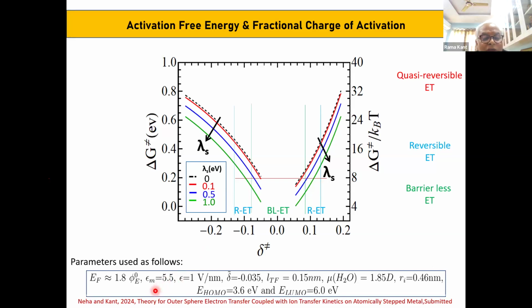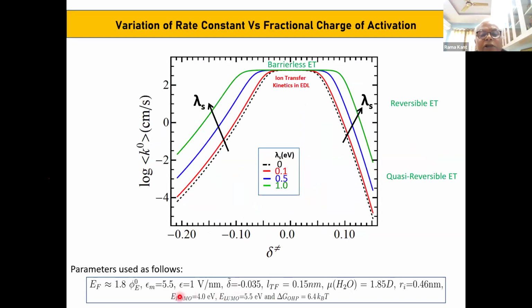To plot this, because we have made a continuum plot, we have assumed that the Fermi energy is approximately equal to 1.8 of the work function. This we averaged over various Fermi energies. It's not true for graphene. For good metals, this formula is a good approximation to plot. Then reorganization energy, Thomas Fermi length, size of the ion, dipole of water, HOMO and LUMO energy: these are the input parameters you require to run this theory and get quantitative values from it.